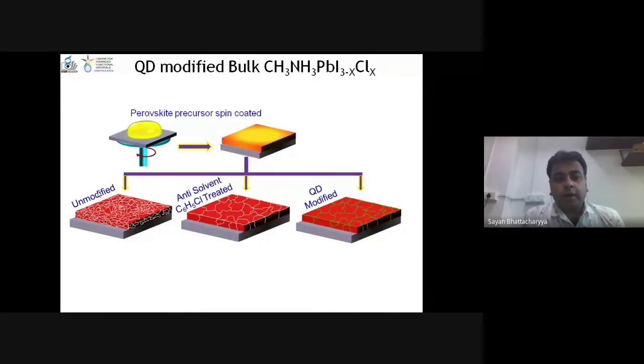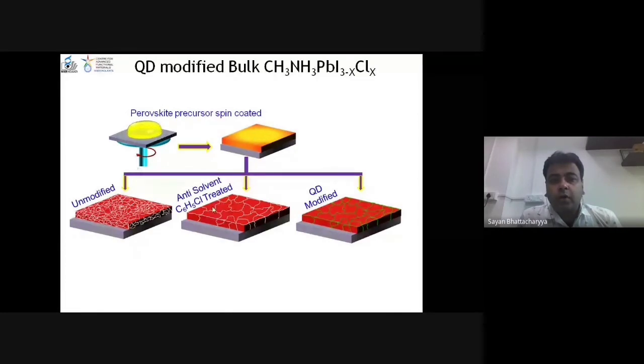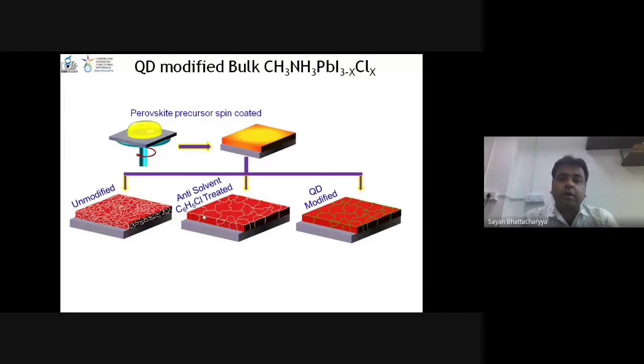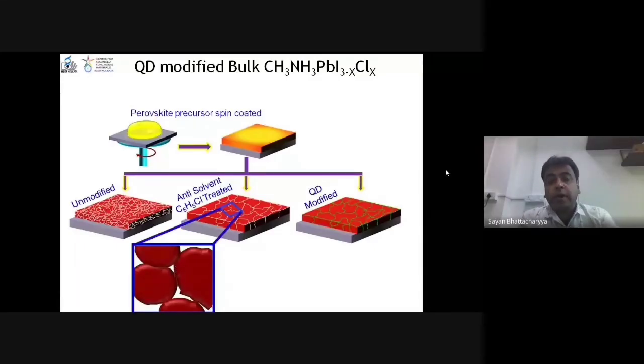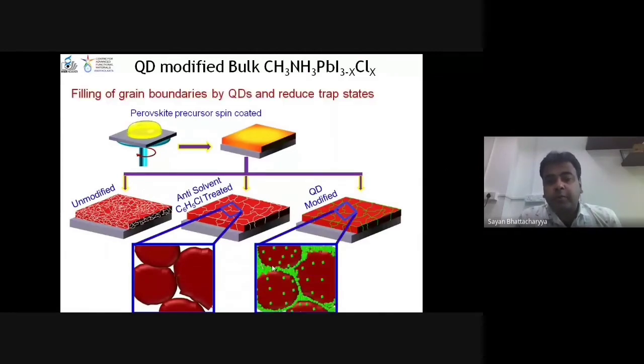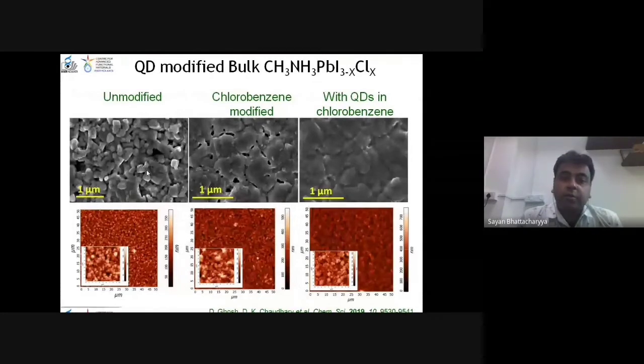So what we did: this is the perovskite here, and here we have modified it with quantum dots, cesium lead iodide bromide quantum dots. We spin coat these quantum dots on top, and we get different layers. This is only with an anti-solvent, which is chlorobenzene, and you see these are the grains. This is a schematic, so you have larger grains. When you put the quantum dots there, they fill the grain boundaries, and they can also sit on top of the grains. So they provide electron percolation pathways between the grains. You see here the scanning electron microscope images.